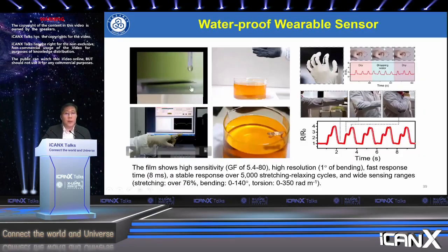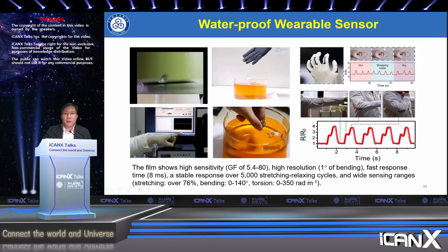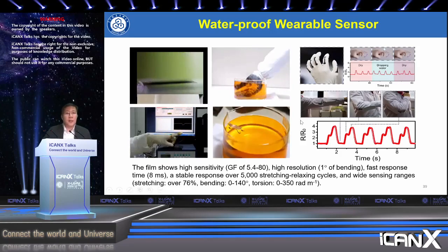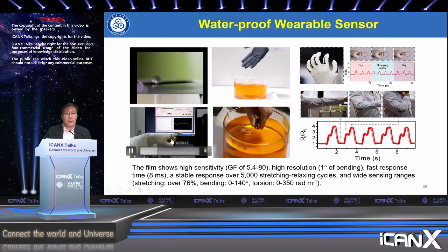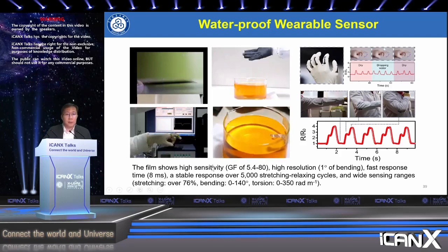And then we make it as waterproof wearable sensors, and we can pattern, coat or print on the glove or the clothes. And you can see that it has very good sensitivity. Even if you drop water on your sensors, there's no interference with your signals. Very high resolution and a very fast response time, about 8 milliseconds.